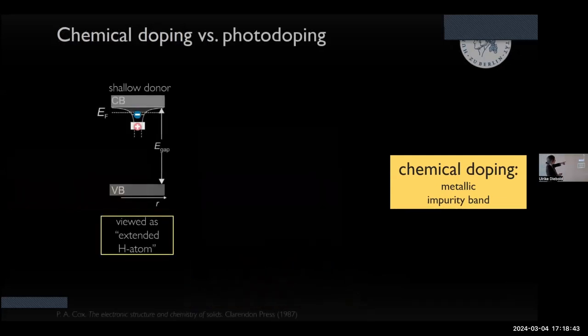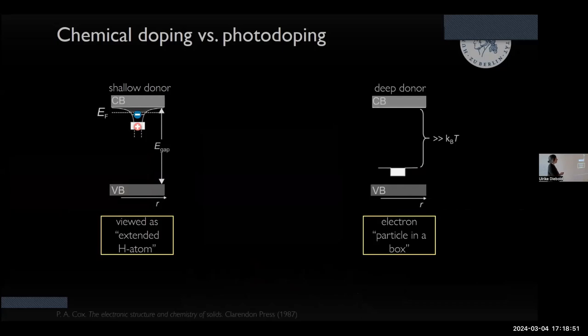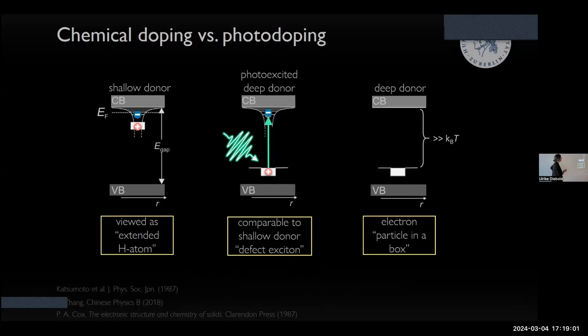Okay, let's get back to the chemical doping. I mentioned the shallow donors, of course there are also deep donors, and they usually do not contribute to conduction simply because the energy barrier is too high. But what you can do is you can photo excite deep donors and create so-called defect excitons, and they will be important when I finally start with my results, because the electron in these defect excitons acts like a shallow donor, and suddenly by photo excitation you can create a situation that is very much like chemical doping. Yeah, so in this correlated community there's a lot of talk about photo doping. This is the only true real photo doping, because it's really analogous to chemical doping.